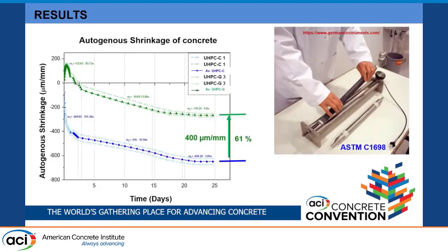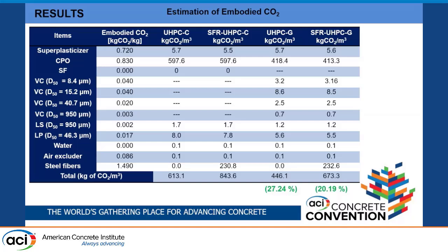Another important thing that we find, we measure the autogenous shrinkage of the concrete, and we see that the vitrified clay originates a reduction of the autogenous shrinkage of 400 microns per millimeter, that is 61%. And this is a very good performance, because this concrete, as a result of the high cement content, normally presents very high autogenous shrinkage, around 1,000 micrometers per millimeter. So it was a very good finding. And also we estimate the embodied CO2, and for the green concrete compared with the reference concrete without fibers, it reached a reduction in embodied CO2 of 27.24%, and in the case of the green concrete with fibers, of 20.19%.